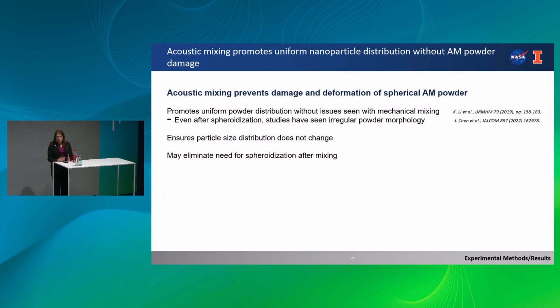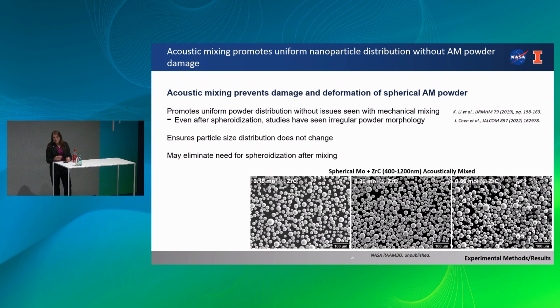So this acoustic mixing really helps prevent damage and deformation to your spherical powder. A lot of studies have used mechanical alloying and then spherodization afterwards, and actually still got non-uniform, non-spherical powder. In our case, you can see that even after mixing a variety of compositions of zirconium carbide and molybdenum, we still have very spherical powder, no major damage to our original spherical particles. And so our size distribution does not change, which means that our optimized print parameters for the pure metal do not particularly need to change. So our hope is that we may not need spherodization after mixing unless we see this nanoparticle detachment during recycling.